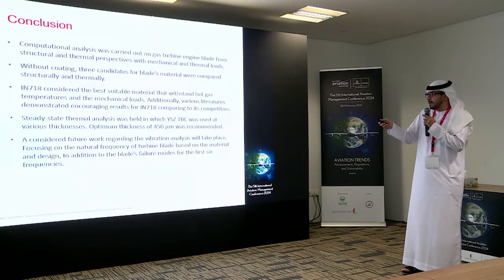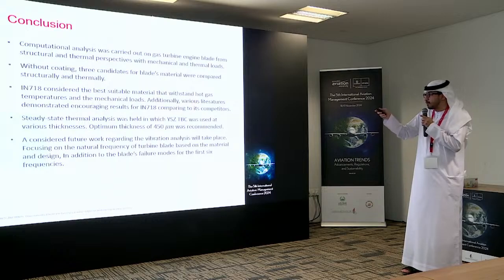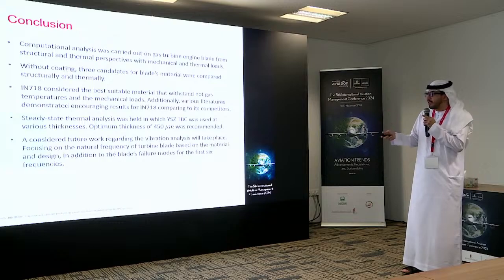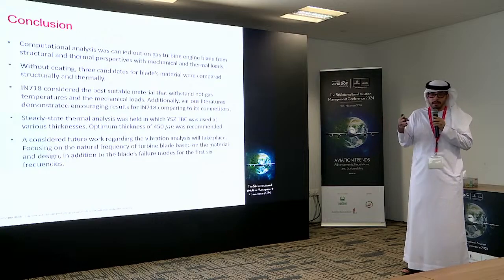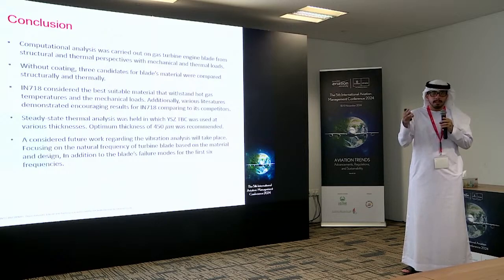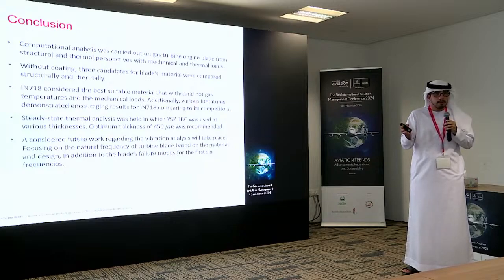A steady-state thermal analysis was held, in which a yttria-stabilized zirconia thermal barrier coating was used at various thicknesses. An optimum thickness of 450 micrometers was recommended. As future work, a vibration analysis will take place. Note that yttria-stabilized zirconia is not the only coating material. There are various coating materials, and this is the beauty of it. You can apply any coating material, simulate it, and see for yourself which one will give you better results.